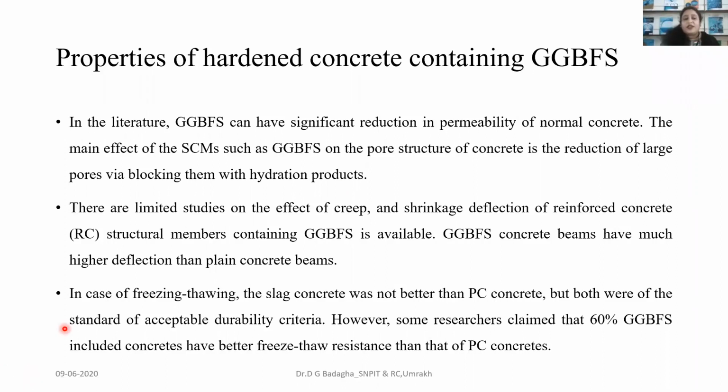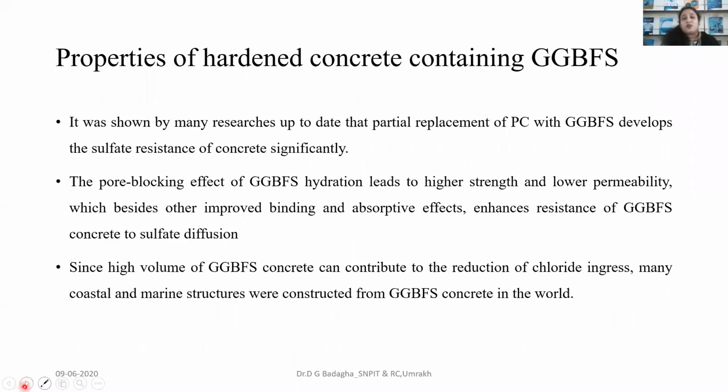Regarding permeability, for that also we have to perform a test, and based on that only you decide. We did the test, and based on that test we came to the conclusion that yes, GGBFS is good from a porosity point of view. If we talk about high volume of GGBFS, like high volume of fly ash in concrete, it can contribute to reduction of chloride ingress. Whenever a coastal region is there, a marine structure is there, in that case GGBFS materials come into the picture for concrete manufacturing, right?